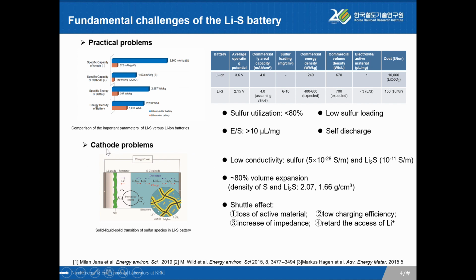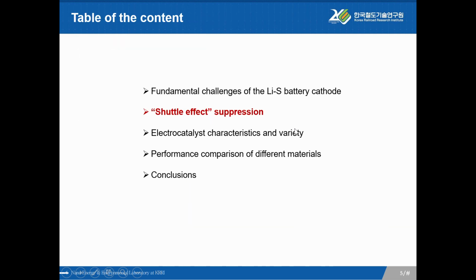All the problems originate from cathode problems. Sulfur and lithium sulfide have a low conductivity and a big difference between the sulfur and the lithium sulfide density. So there is a serious volume expansion. Also, the key factor is the shuttle effect. It will result in active material loss and low charging efficiency, impedance will be increased, and access of lithium ion will be retarded. So what's the shuttle effect?